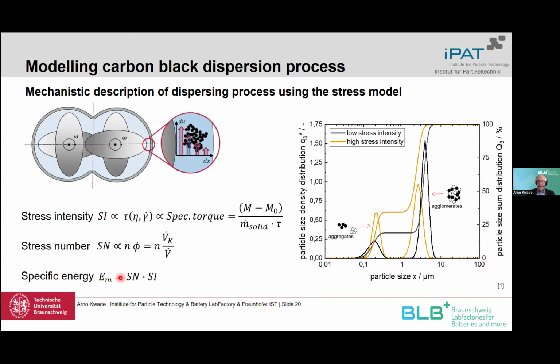And what we can see is that if we have low stress intensity, then we still have a higher number of agglomerates and a lower number of aggregates. If we increase the stress intensity with the same comminution or dispersing time, then we have a lower amount and also smaller size of agglomerates, but we have many more aggregates formed here.